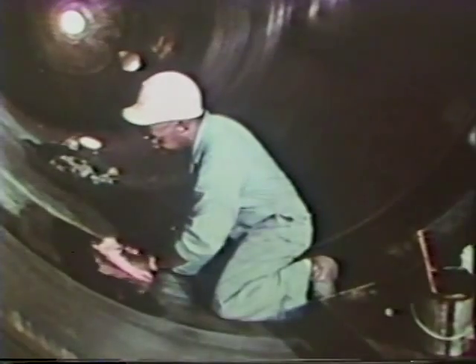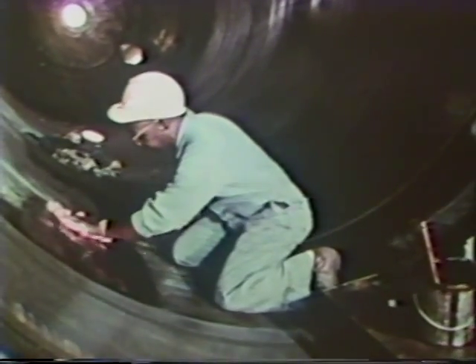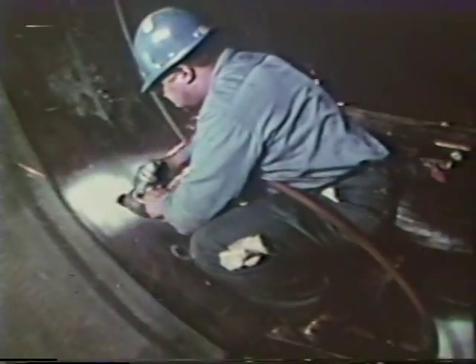In a different technique, a red dye is painted on the metal surface, then wiped off. A layer of white paint is sprayed over the same area. If the red dye bleeds through, a flaw is detected. The defect, immediately noticeable, is then repaired.